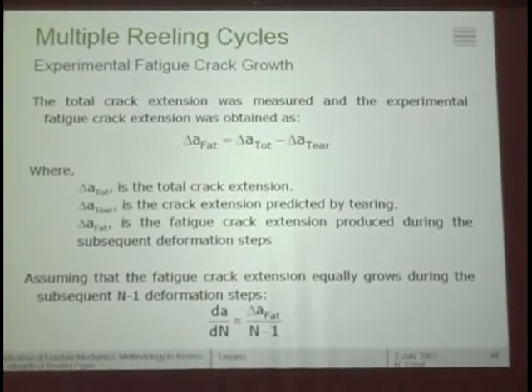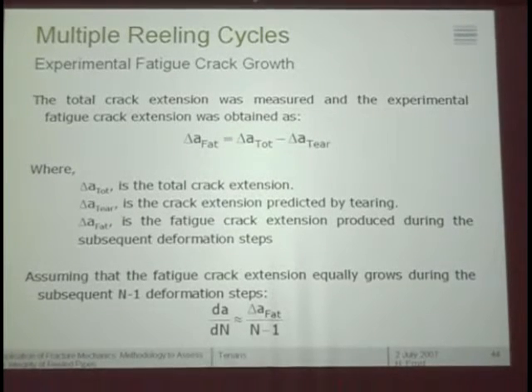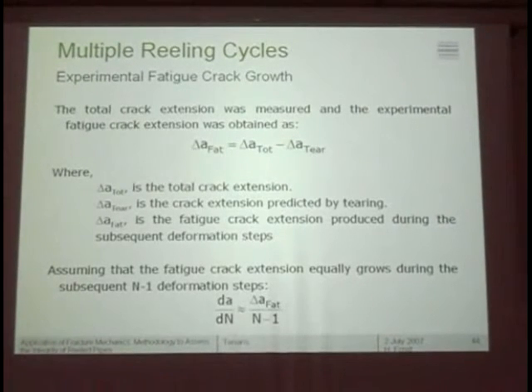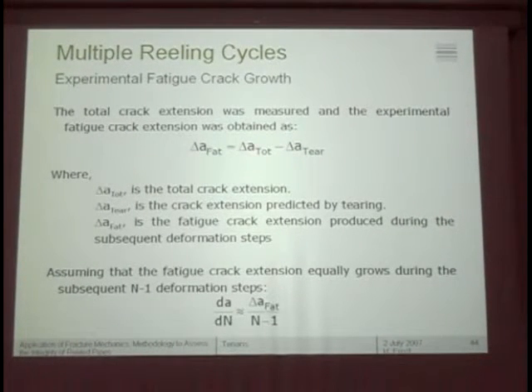And we did take a very bold approach. Basically, after doing all these cycles, we measured the total amount of crack extension, complete total amount. We subtracted from this delta A total the one that we obtained from tearing, that is from the resistance curve, and the difference between the two we call delta A fatigue, because we are considering the linear addition of these two models. It is simplistic, but it is the best we could do at this moment. And basically, after we had this delta A coming from fatigue, we divided that by n minus 1, number of cycles minus 1. We decided that the first one is only tearing, the others contribute with fatigue, although I said before that even with 2, you didn't see fatigue, but just for the sake of being conservative, we put that cycle in there too.